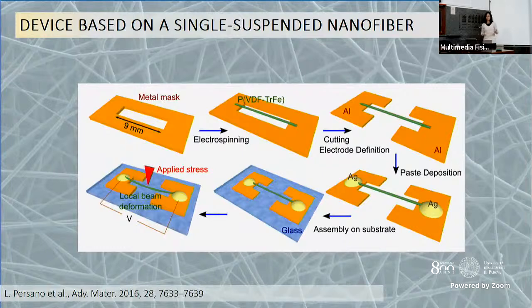This is just a scheme to show how we build the device very easily. The final form of the device is here reported. So you have the fiber, the beam, the diameter was 700 nanometers. The length of the fiber in the device was up to 1 centimeter. And we delivered localized force in this direction by the use of a nano indenter. And of course, we measure the voltage generated from the fiber at the edges. So in a configuration which is not the standard one, because in the standard one, if I apply the force in this direction, I should get the voltage with the electrodes on both ends of the fibers, while we are going to take voltage here, so at the edges of the fibers.